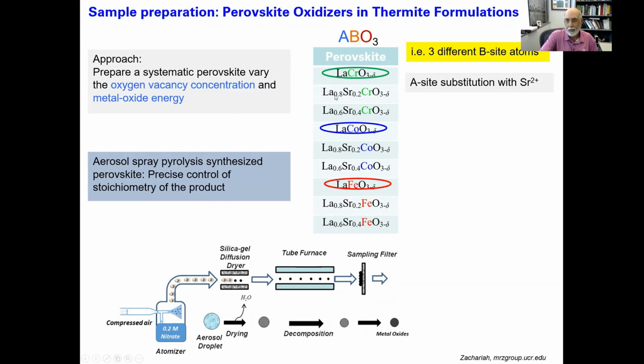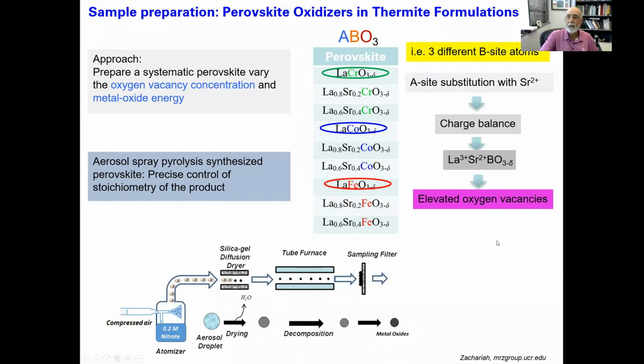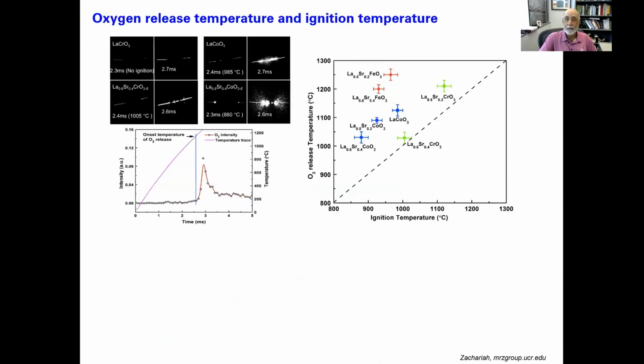Lanthanum is a +3. If I put strontium as +2, that means I've put less positive charge. And by charge balance, that must mean I'm going to have to put less oxygen in. So by putting strontium instead of lanthanum, I'm going to force the system to have less oxygen by charge balance. So now I can put vacancies into the structure in a very controlled way. And we're going to see what that does.